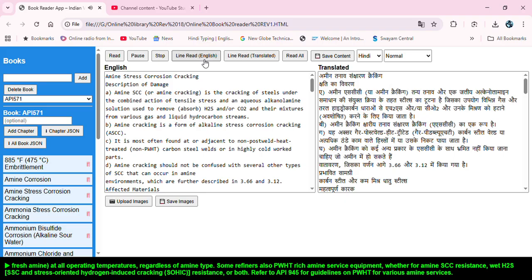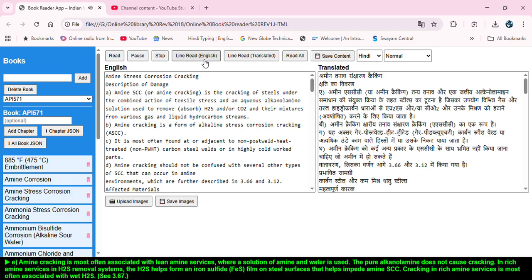regardless of amine type. Some refiners also PWHT rich amine service equipment, whether for amine SCC resistance, wet H2S SSC and stress-oriented hydrogen-induced cracking, SOHIC, resistance, or both. Refer to API 945 for guidelines on PWHT for various amine services. E. Amine cracking is most often associated with lean amine services, where a solution of amine and water is used. The pure alkanolamine does not cause cracking.